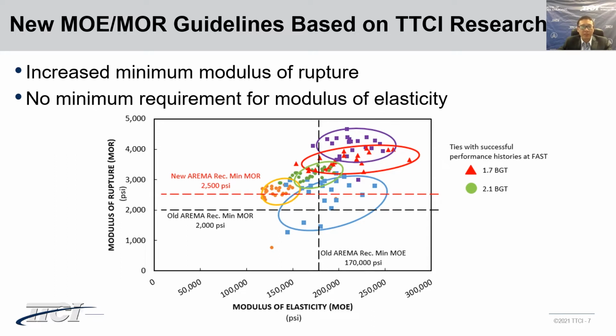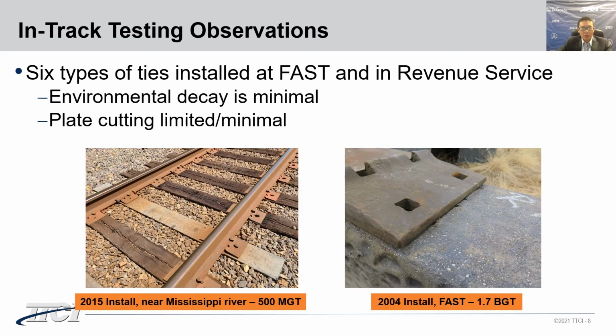Therefore, we believe there's little evidence to suggest that higher MOE is indicative of in-track performance of composite ties. Based on this, the minimum MOE was no longer a recommendation in the older AREMA manual, and it was replaced with a recommended range in 2018. In-track testing also observed that the environmental decay is minimum on the tie materials for all types of composite ties.